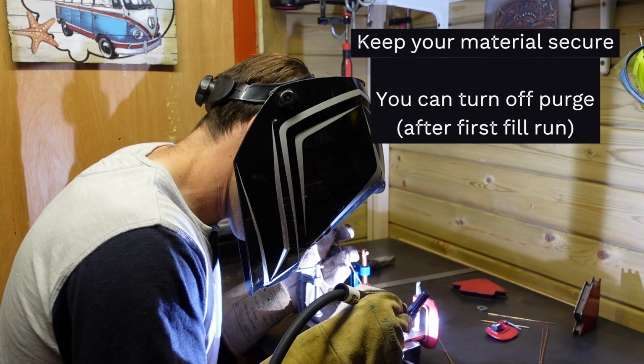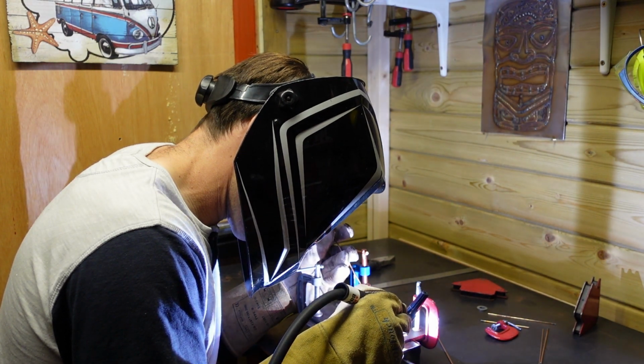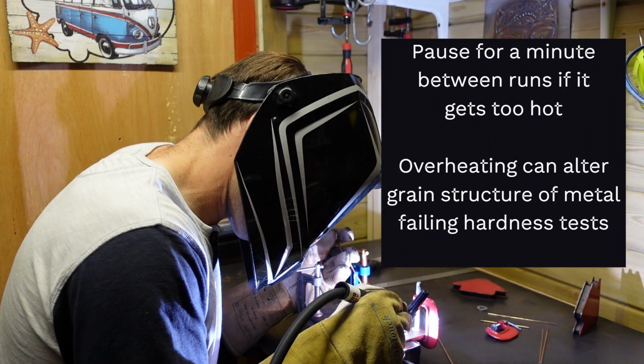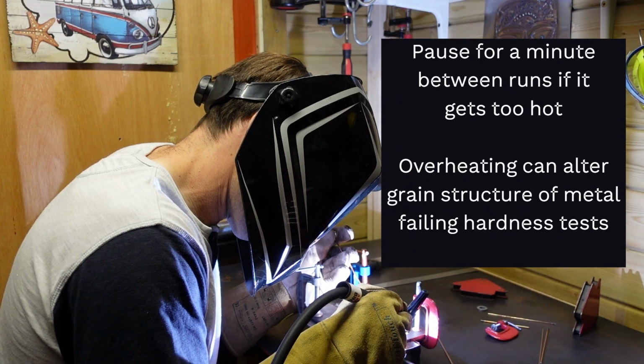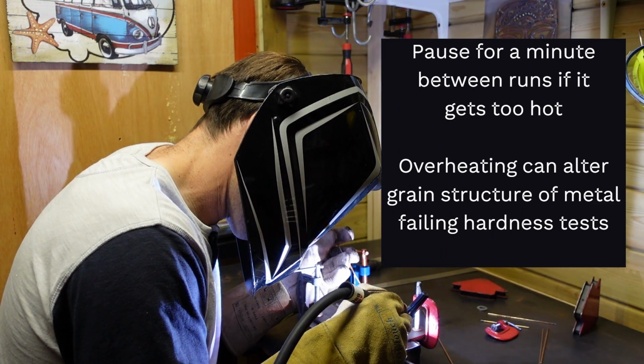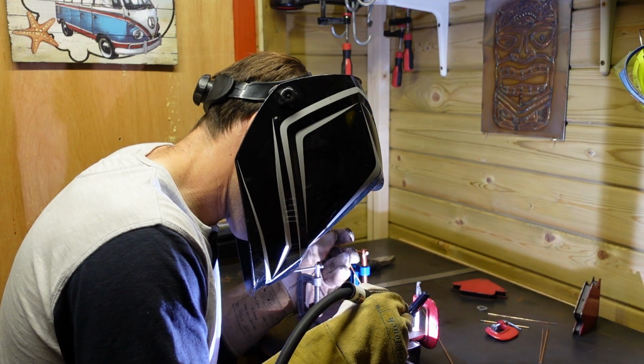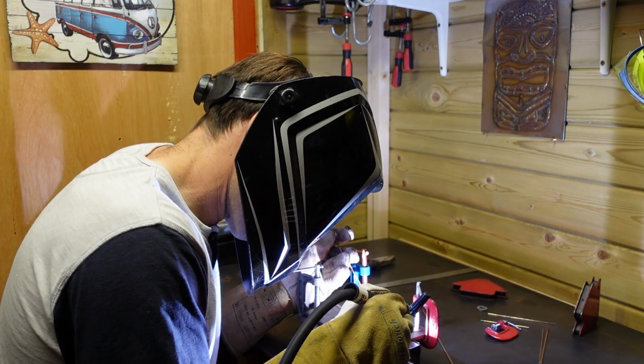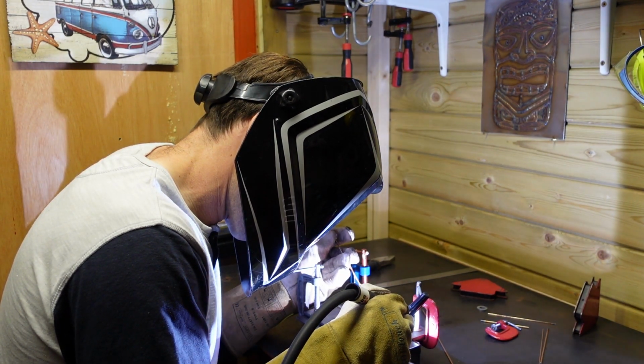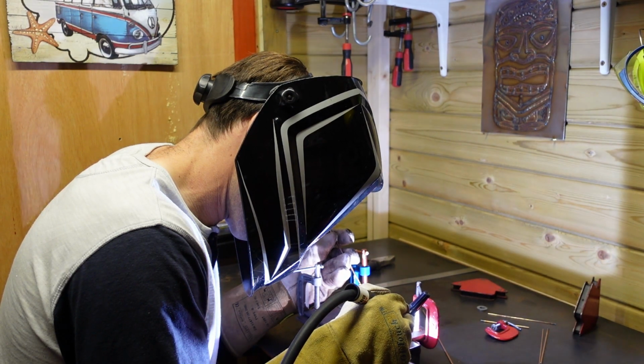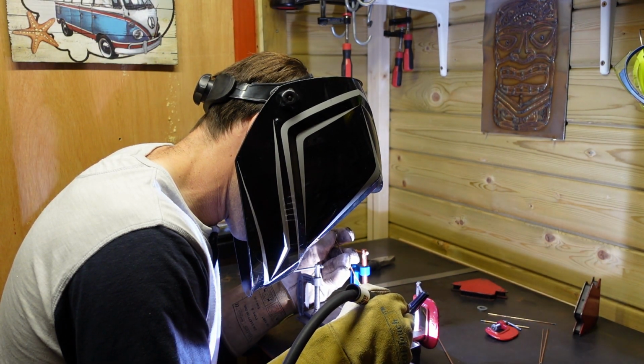Do not let your test plate overheat, as you could cause problems which may pass x-ray but will fail with more destructive inspections such as hardness checks or bend tests. Going too hot can change the metal's grain structure, causing brittleness and other metallurgy issues, not to mention the constant warping through heat. Okay, filled, ready for cap. I'm going to let it cool down a little bit.